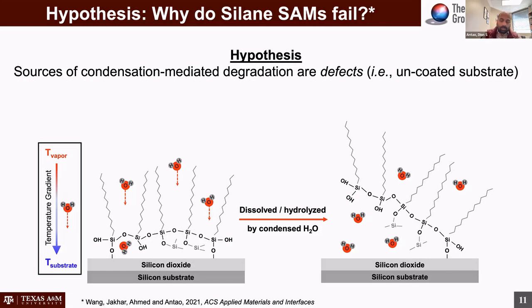What we found as a common thread or trend was that invariably in all the surface chemistry literature, they tended to minimize the amount of water present in the system, because it's well known that these silanes tend to hydrolyze and cross-link in the presence of water, and they don't really form monolayers on the surface, which is a single layer of the coating. They tend to form multi-layers.